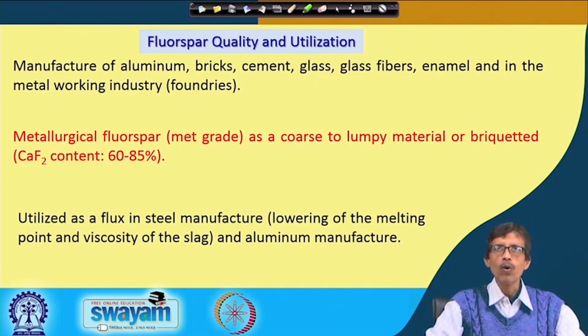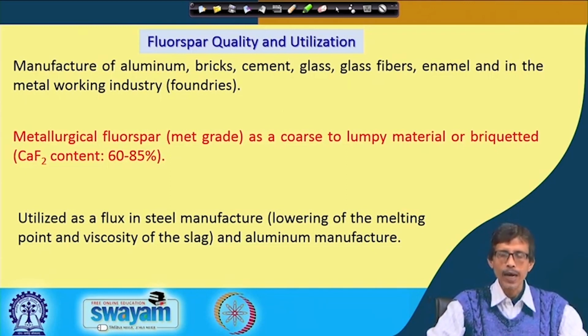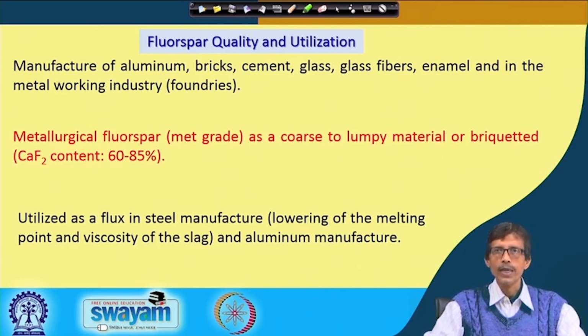When we have an ore or mineral in our hand, and if we try to get a melt out of that, we add some amount of fusion mixture. And if calcium fluoride is given to it, it is basically functioning as a flux, which is giving a low melting point for the ore material. So, we can lower the melting point, that means your expenditure for getting the higher temperature would be less, and also the viscosity of the slag is reduced.